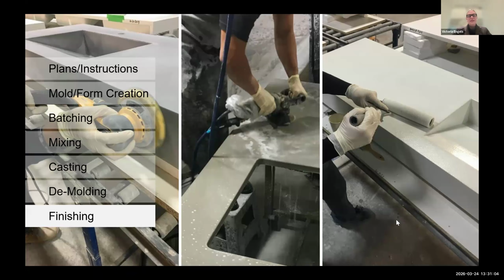A thorough finishing process will include at least these steps. So first you'll have wet polishing, where the piece is smoothed out, sharp edges are softened, and a uniform surface is achieved. Next is filling. This step involves plugging and filling any pinholes on the surface with concrete of the same color, followed by sanding. This is where any plugged pinholes become seamless with the rest of the surface. And finally, sealing, which is the most critical step. Because concrete is inherently porous, it should always be sealed. The material and method used to seal concrete is key in determining how resilient the surface is going to be.